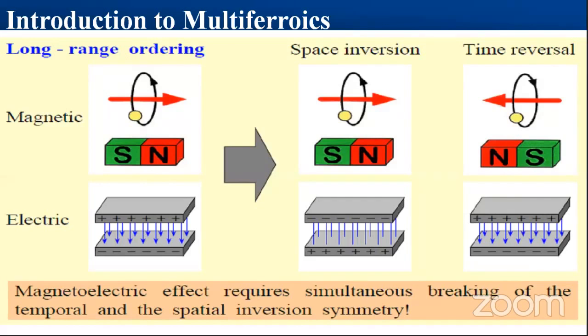Okay. And also, on the long range ordering, if you want to switch your magnetic polarization, you need to reverse time, so you need to switch the electron spin state, which is called time reversal. And if you want to switch the electric polarization, you are going to invert the space, space inversion. So in the case of multiferroic materials, you need both space and time inversion, which is very difficult to have in the same class of material. So that is why having a multiferroic material is very rare, and having this property at room temperature is very difficult.